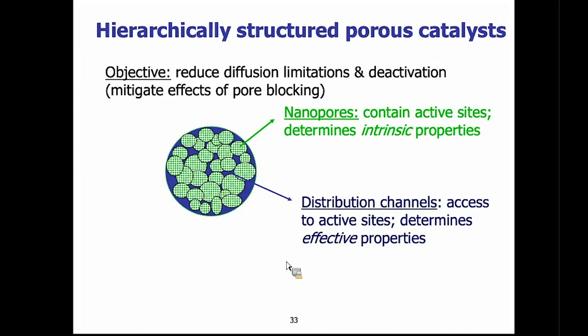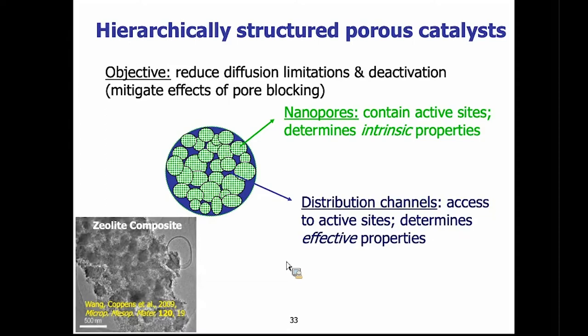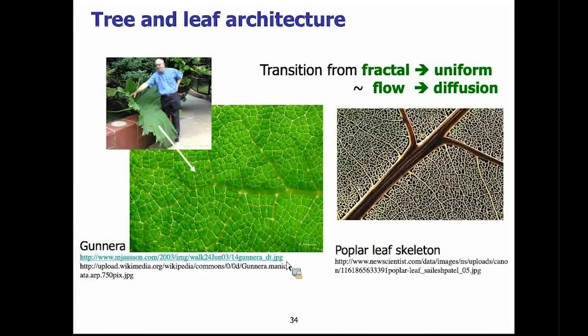So in porous catalysts that are used in many catalytic processes, there are often diffusion limitations. Molecules can't access these active sites in the narrow pores. And you can also have blockages of pores. And so one needs distribution channels. There's been huge progress in synthesizing and designing new hierarchical materials like zeolite composites with controlled pore structures at multiple scales. But the question is still, what should they be like? And when we turn to trees and leaves, you look at some very large leaves and you see that they start with a fractal architecture. But then at a small scale, they turn into something very uniform. And when you look at the leaf on the right, a poplar leaf, you see this very uniform structure in between, where the cells are.